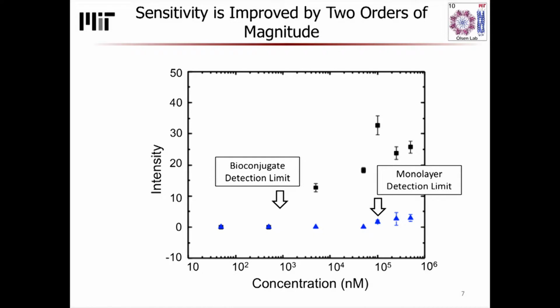So here we have the fluorescence intensity at the surface by this very simple readout plotted against concentration. And the monolayers give a very, very low response because there's not a lot of protein. But these three-dimensional nanostructures give a very high response and a limit of detection that's about two orders of magnitude lower than in the monolayer system. And so this simple proof of concept illustrates the ability of building with nanotechnology instead of using just simple adsorbed protein monolayers to transformatively improve the sensitivity of biosensors.